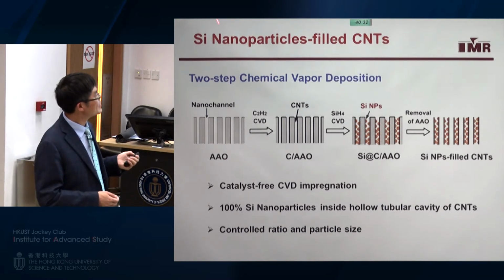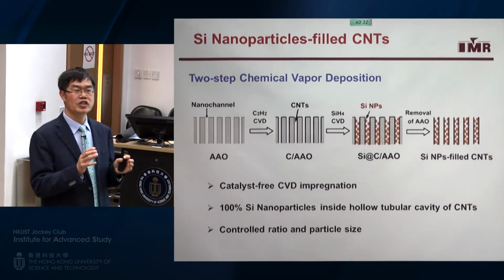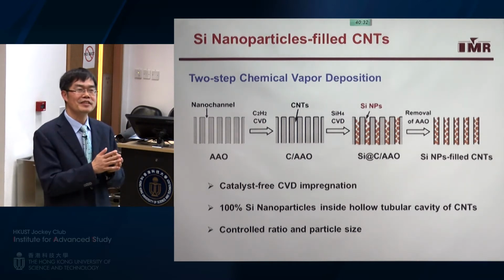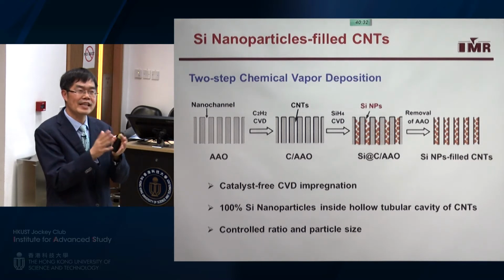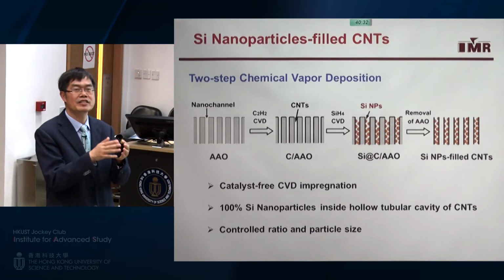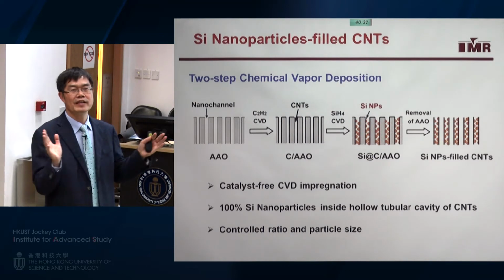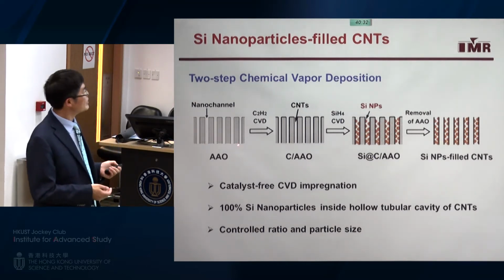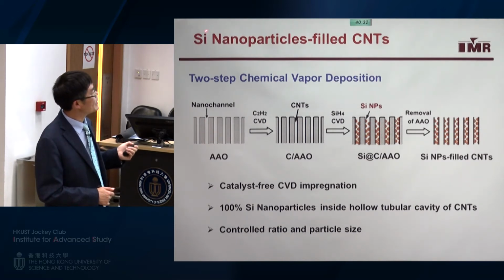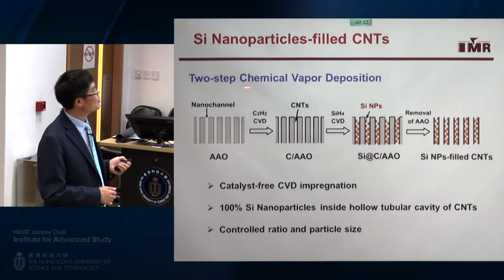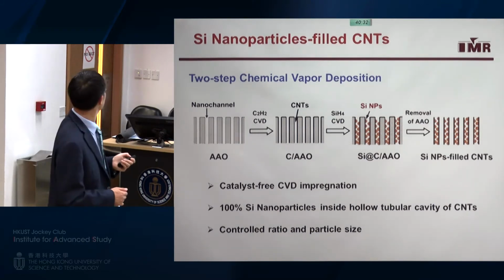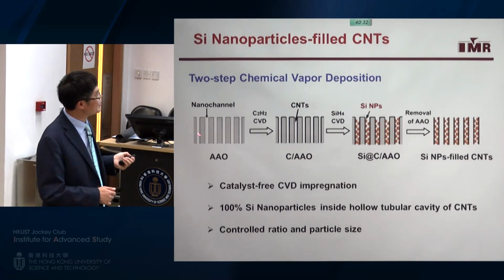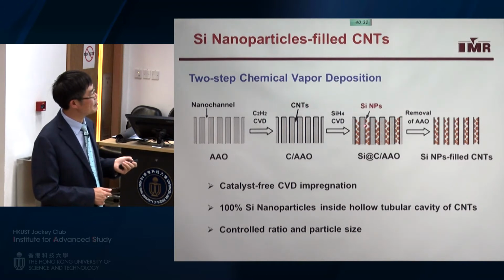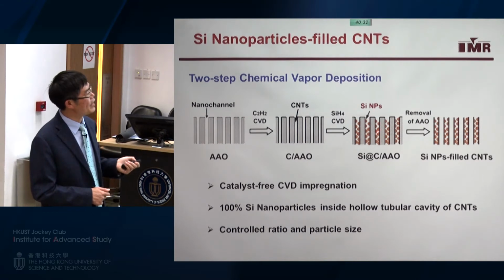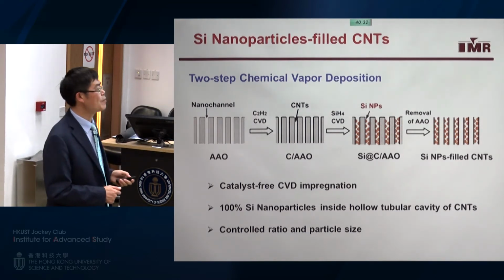But the problem is silicon has a very high volume change, expansion during charge and discharge. That means the electrode will be very easily damaged during charge and discharge. Then after just a few cycles, the battery will fail. Therefore, we needed to control the volume change of silicon particles. So we tried to fill silicon nanoparticles into carbon nanotubes, as I show you here. We use this AAO as a template, and then we fabricate carbon nanotubes and fill silicon into them in nanoparticle form, and then we remove the AAO. We get this 100% silicon-filled carbon nanotube hybrid material.